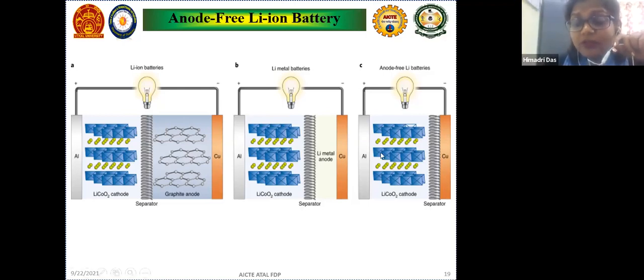The cathode material will be nearly the same. It may be NMC or lithium cobalt oxide, or whatever the best cathode material is that we take as per our application. So the anode will be just nothing, like copper foil, with neither metal nor graphite nor any other oxide. It will be just a simple copper layer, a copper current collector, for the anode free battery.